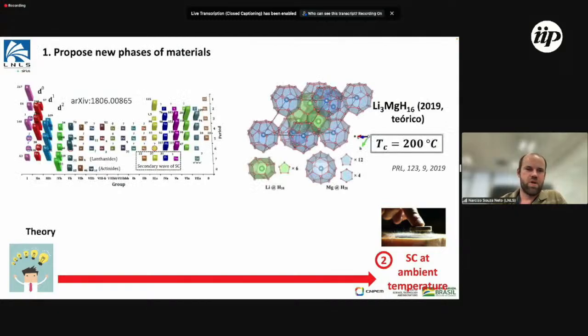The first thing that we need for that is actually theory, where there are a lot of theory groups that are proposing new phases of materials with ab initio calculations, combining different elements with hydrogen, for example, and seeing which of those would give the highest superconducting temperature. Ab initio calculations and some estimates and approximations of some equations, McMillan equations, relating electron-phonon coupling, to predict the superconducting temperature.